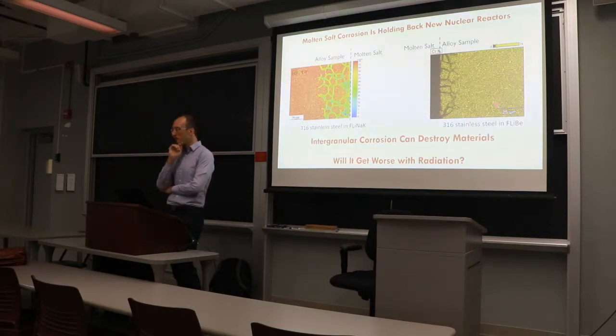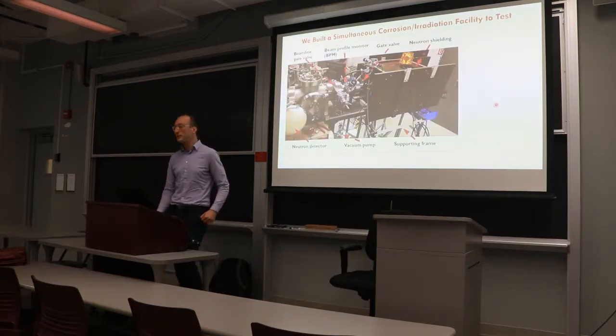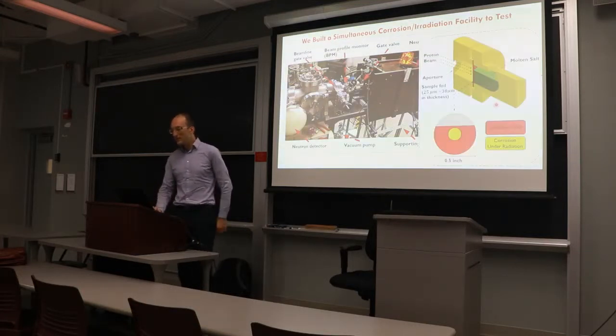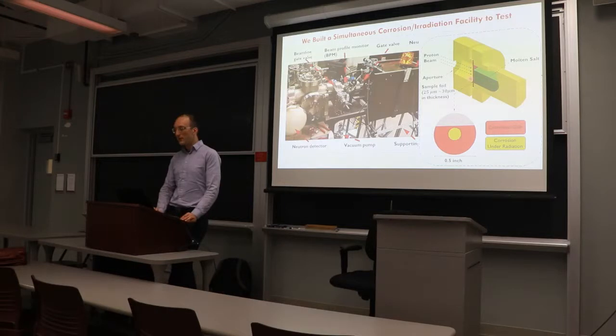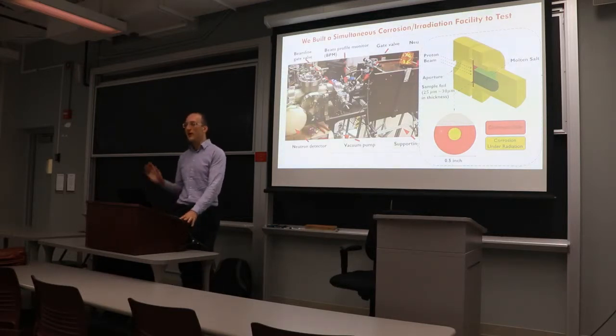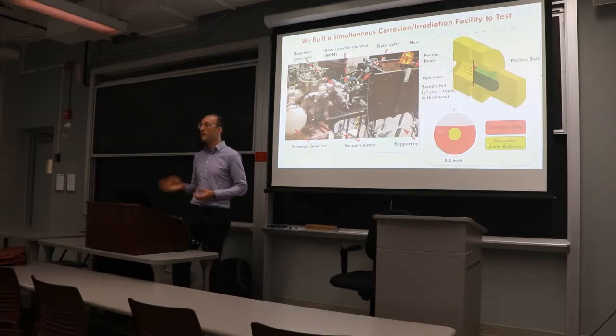Couldn't find much published, but explain that a little bit, right? Yeah. So we built our own beamline, which is going to look suspiciously like the one that Professor Hosemann built at Los Alamos. It allows you to have a vessel of molten salt with a thin foil sample and a proton beam blasting through it at the same time. So the protons go through the metal into the salt, so you just induce radiation damage and some funky salt chemistry effects. And you get a built-in control sample, because by masking off your beam, you get a corrosion and irradiated region in the center, and a corrosion-only region on the outside. So you have an apples-to-apples comparison in the same test, with nothing else varying except the amount of radiation hitting.